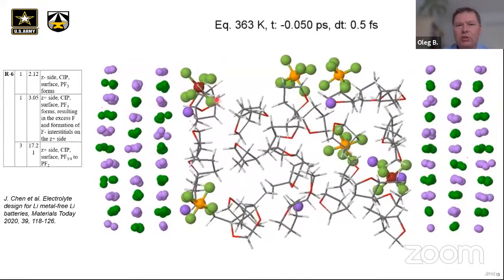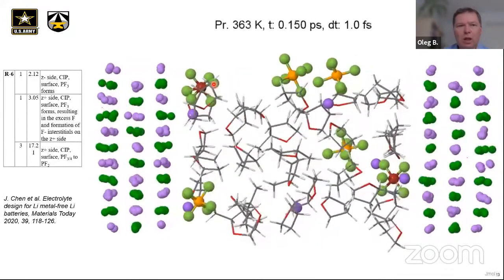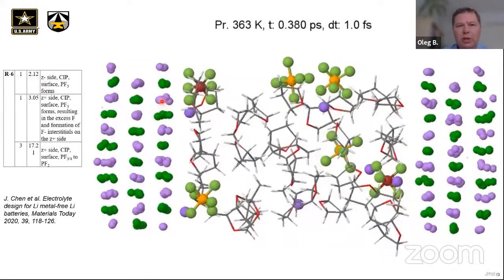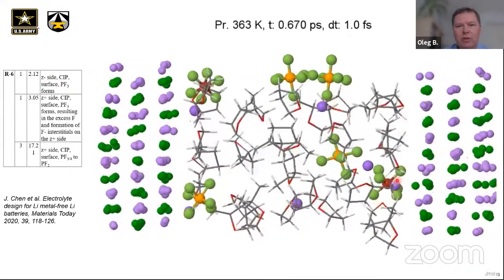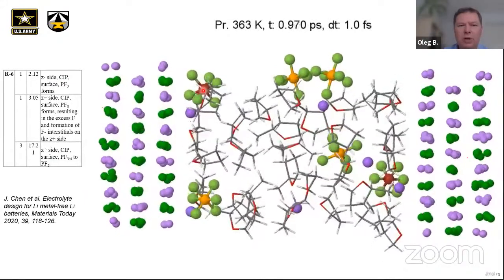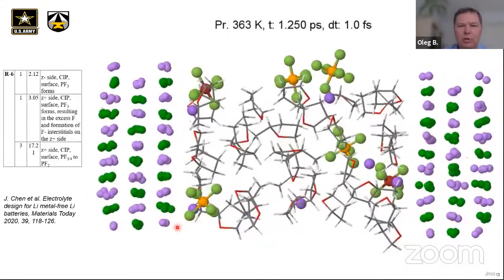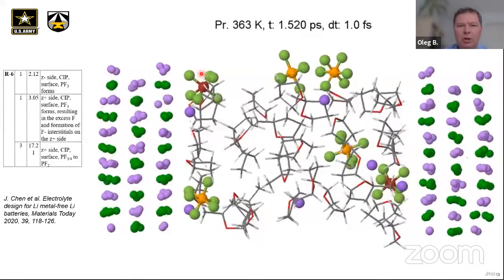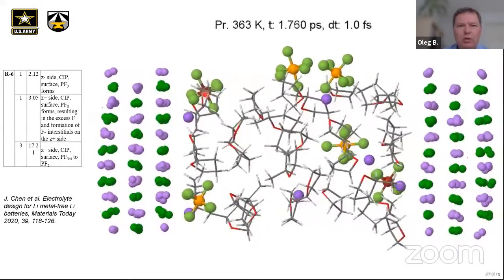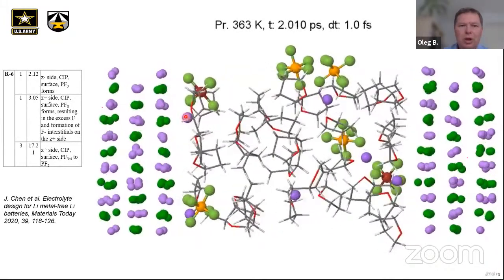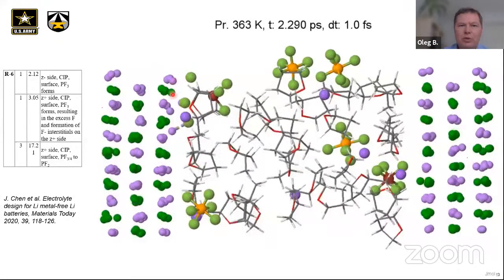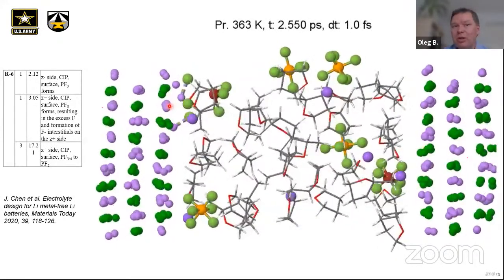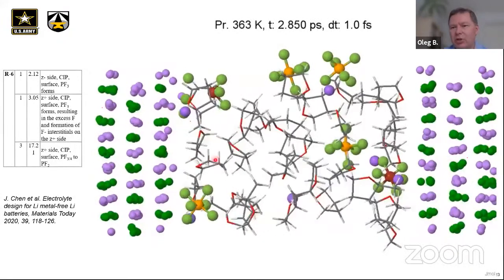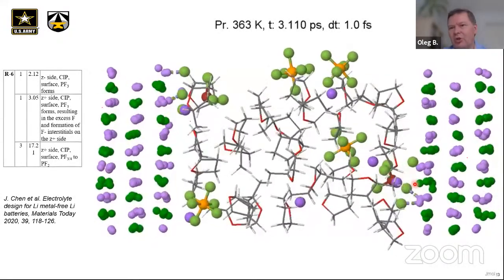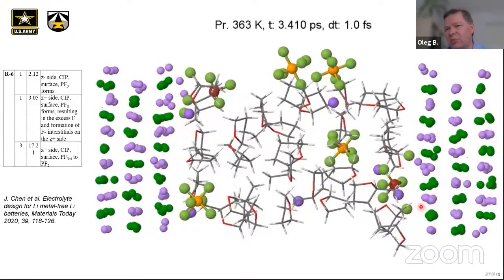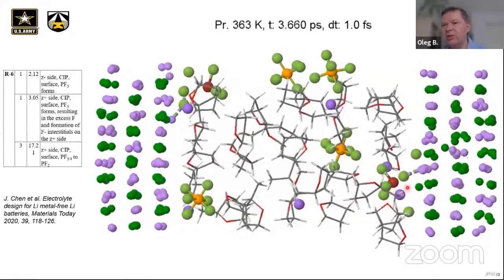Let's look initially at this first PF6. It's going to decompose at 2.2 picoseconds. After that, we're going to look at this PF6. It forms a contact ion pair, and through the periodic boundary conditions at the other interface, there is also another lithium next to it. So now we're getting close. It comes closer. It's important that there is LiF. They participate in the reaction. Now let's look at the other side. The other PF6 undergoes the same decomposition reaction with PF3 forming, but there is something else.